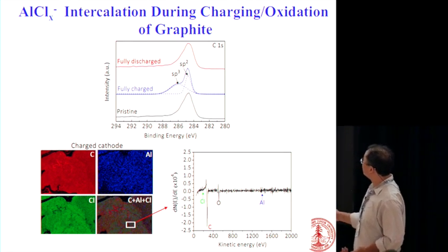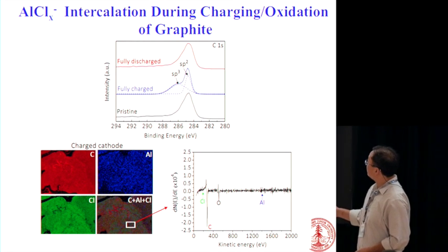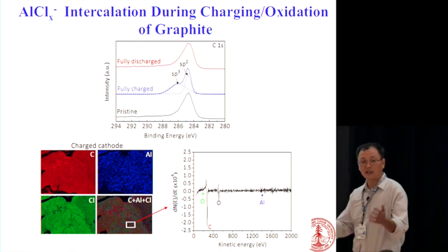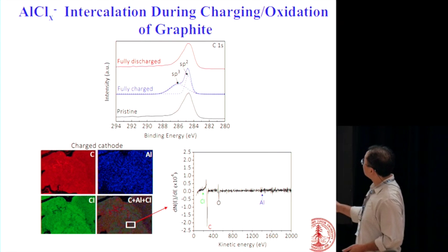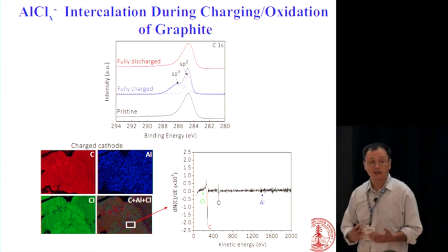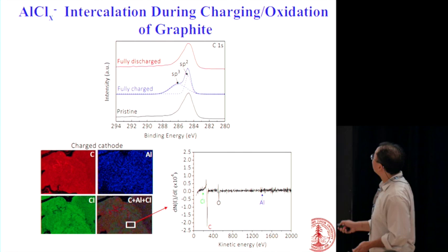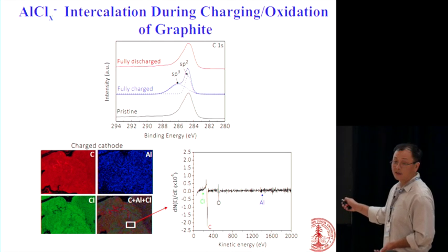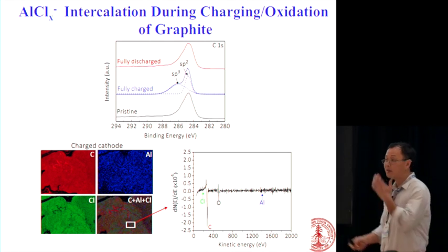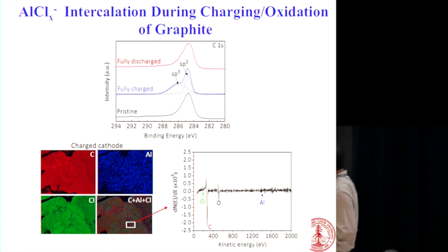So this is a pristine graphite. When it's charged, the anion is in. Graphite is oxidized. You see that shoulder, that's the oxidation peak of carbon. And when you discharge it, it reverses. Okay, so a fairly reversible redox reaction.